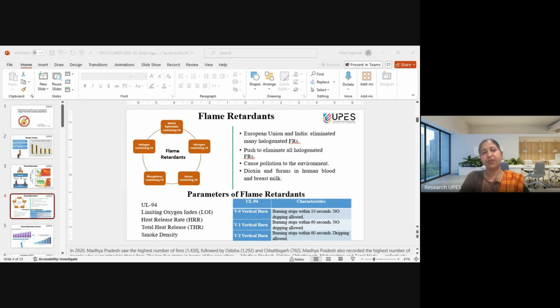Among these, from the industrial point of view, UL94 is the most important test, which is a vertical burning test. In this, three ratings are there: V0, V1, and V2. We keep the polymer in the vertical state and burn it with butane. If the burning stops within 10 seconds and no dripping takes place, then it passes the V0 specification. If burning stops within 60 seconds and no dripping takes place, then V1. And if burning stops within 60 seconds, but dripping is also there, then it is V2. So our efforts are always to achieve V0 specifications.